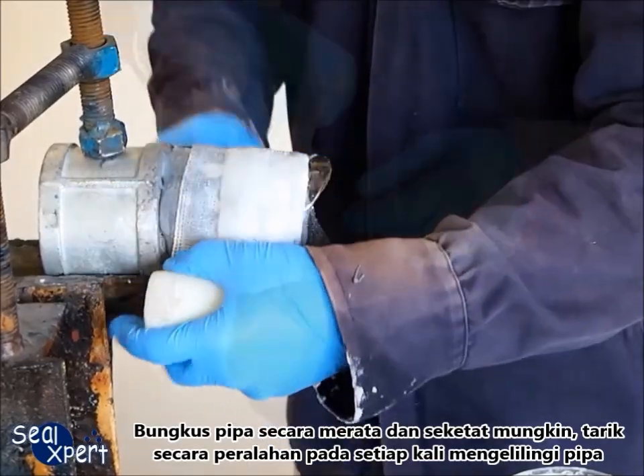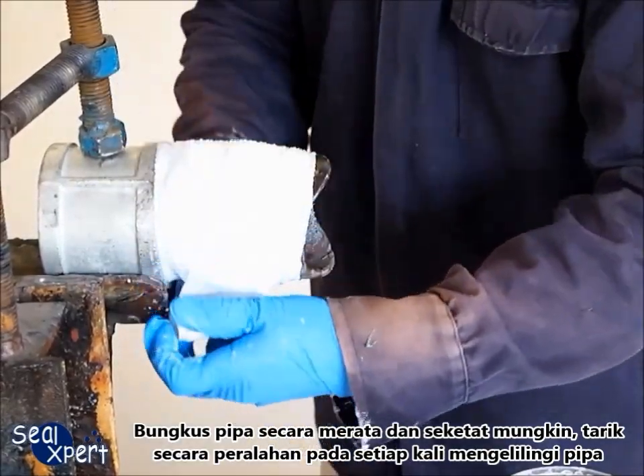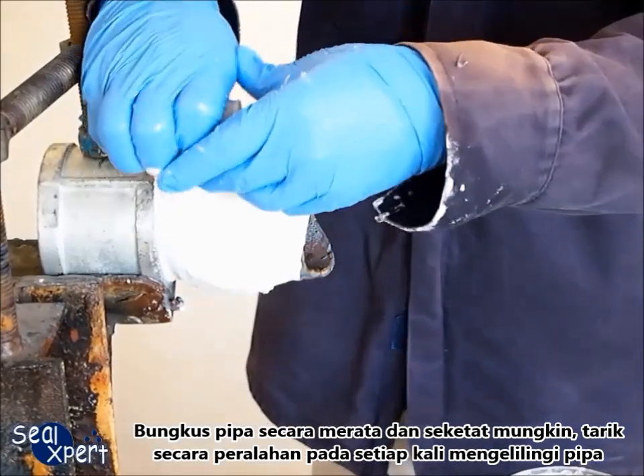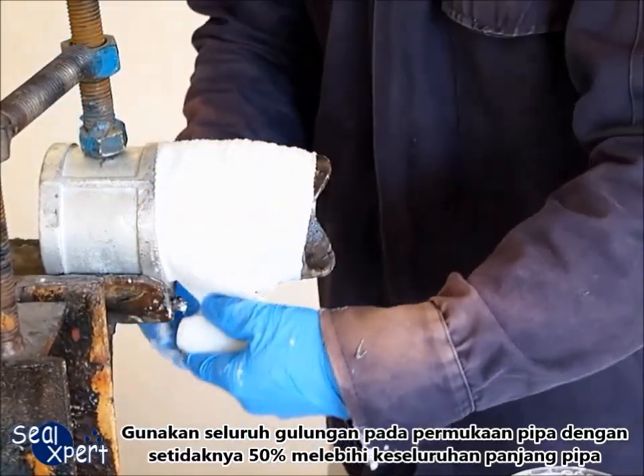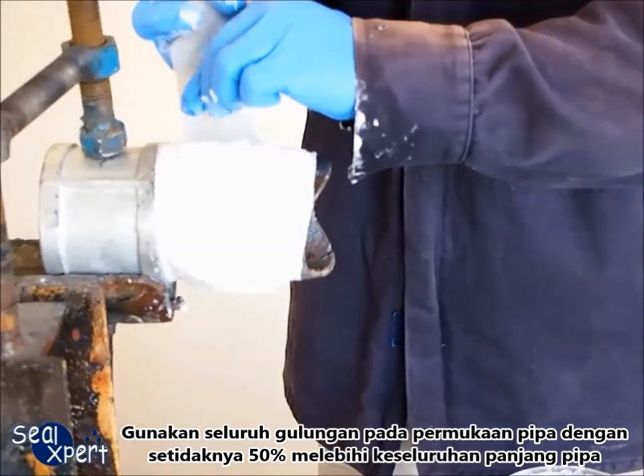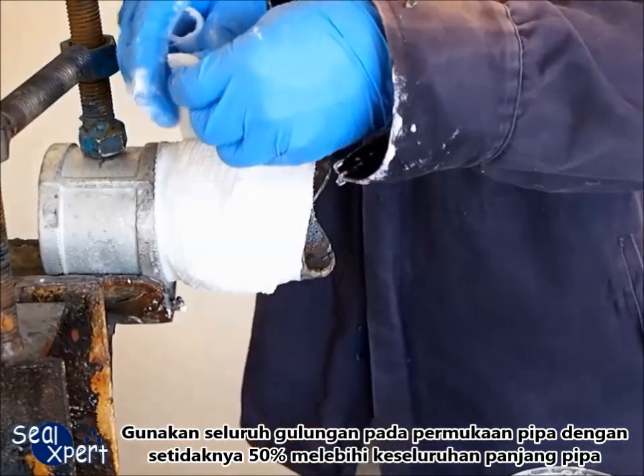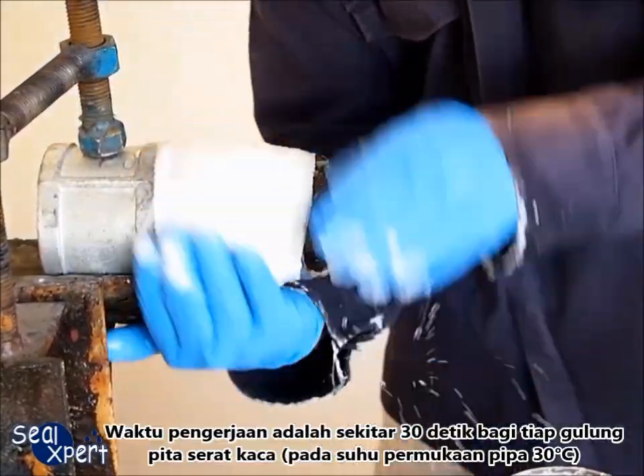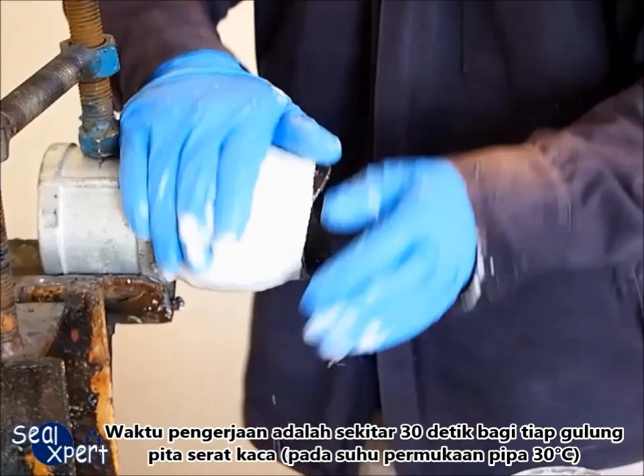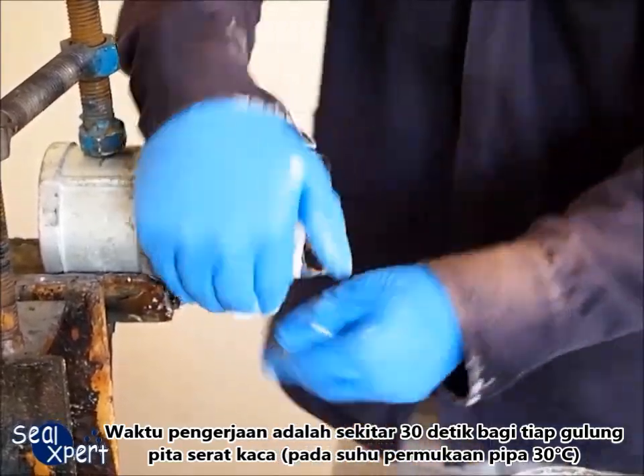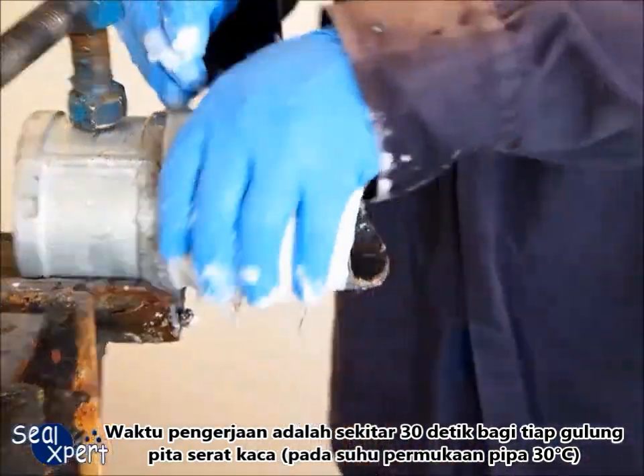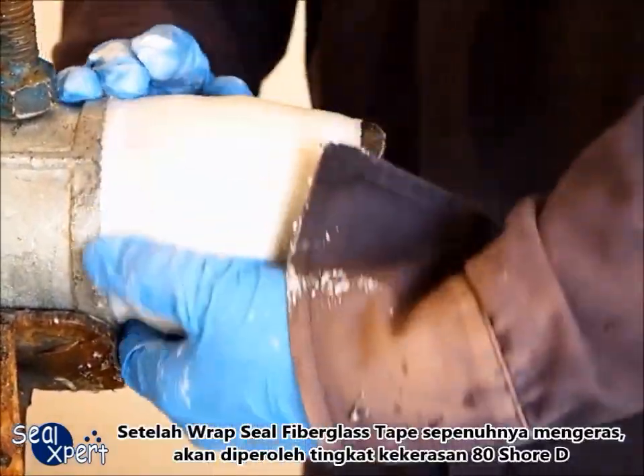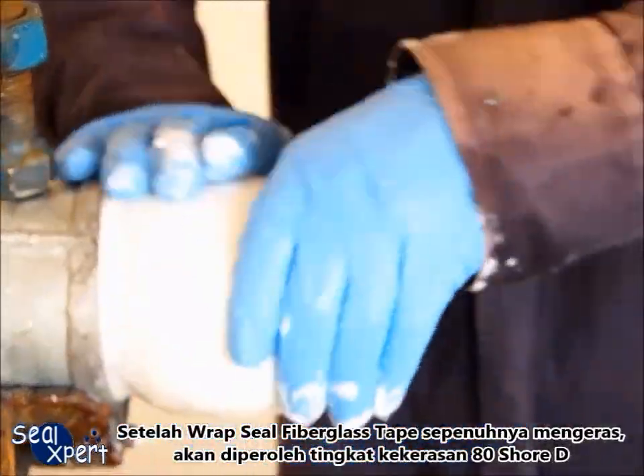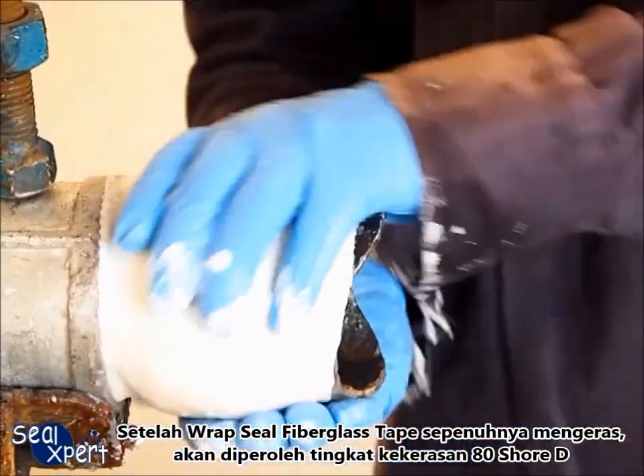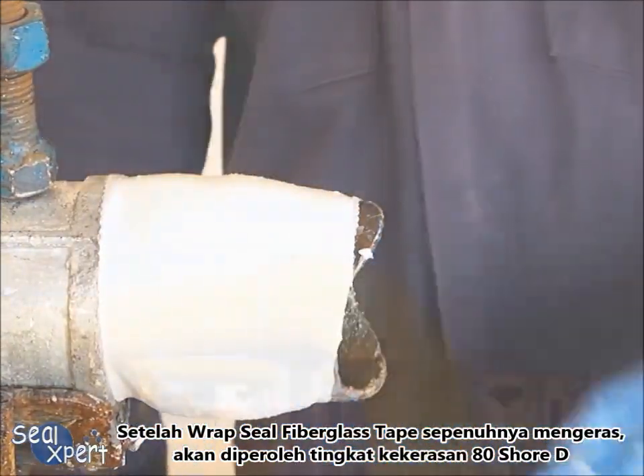Wrap the pipe as evenly and as tightly as possible, pulling slightly after each round of wrapping. Apply the entire roll over the pipe surface with at least 50% overlap for the entire repair pipe length. The working time is approximately 30 seconds for each roll of fiberglass tape at 30 degrees pipe surface temperature. After the wrap seal fiberglass tape is fully cured, it will attain approximately 80 Shore D hardness.